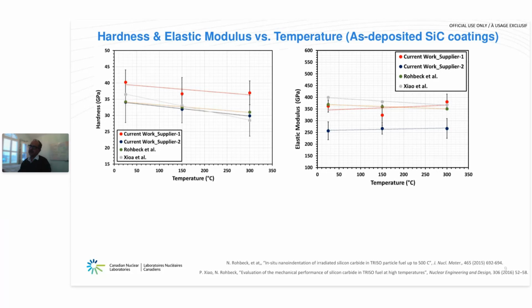So first, from supplier one, the hardness for these silicon carbide coatings was about 40 GPa on average at room temperature. And for supplier two, again, the hardness was slightly lower, but was still close to about 34 GPa or so. These extremely high hardness values are typical of ceramic coatings, in particular at room temperature, where the lattice resistance is still very high and results in